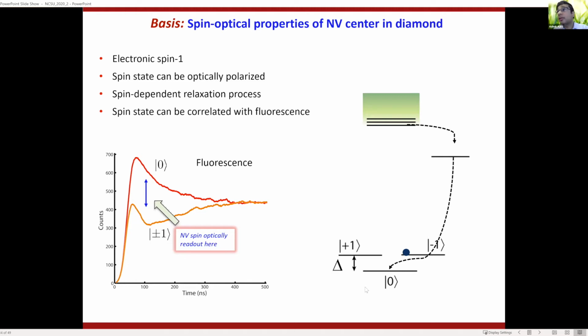And so this setup sets up a bias in the system. So if you keep the light on long enough, and you don't need to keep it too long, but if you keep it on for about a microsecond, then all the population is selectively shunted to this ms equal to 0 state. So you can produce electrons which are highly polarized, almost 100% polarized, all in this one state. And along the way, you can also read out the electron spin state, because if it started from here, it would produce lower fluorescent counts, and you can read out that the electron started from here.